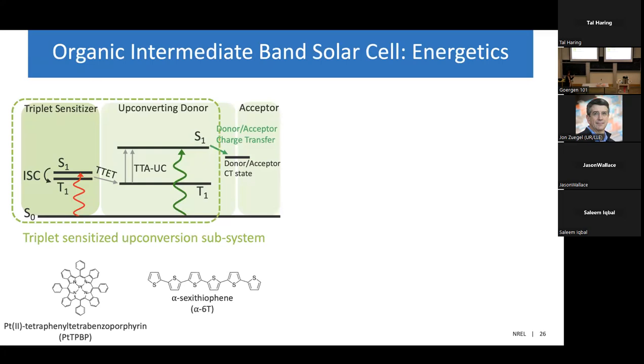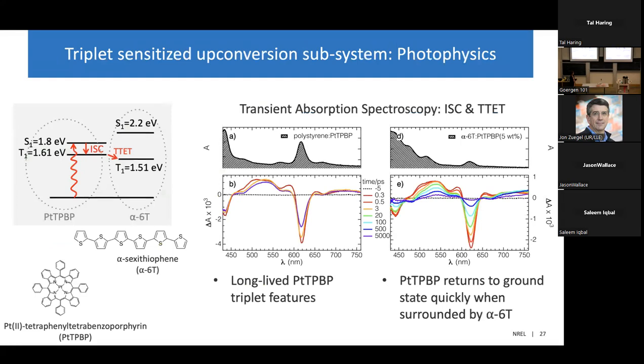So we want to prove that the photophysics of this upconversion subsystem are operative. And to do that, we turn to transient absorption spectroscopy. If anyone's not familiar with this technique, it's a pump-probe spectroscopy technique that allows you to observe the evolution of excited states in your system. And when we look at the transient absorption spectra of just this platinum porphyrin compound by itself, when it's been embedded in an inert matrix and all the molecules are separated from one another, we see really long-lived triplet features. So the purple trace here is 5 nanoseconds, or 5,000 picoseconds, and you can see that there's significant amplitude at 5 nanoseconds.